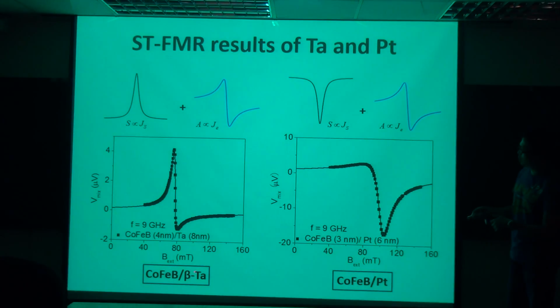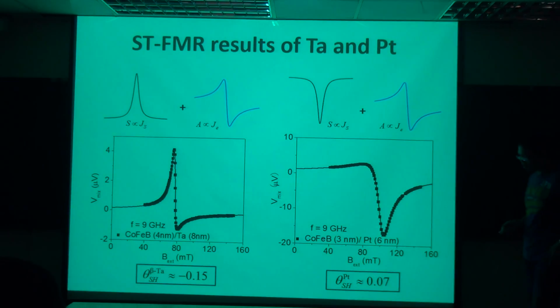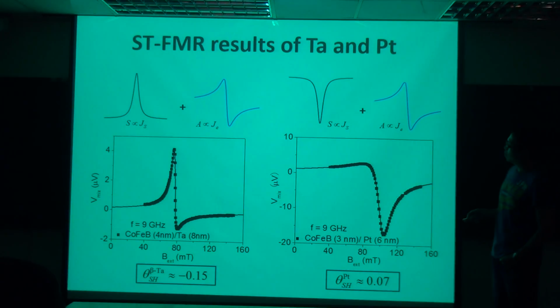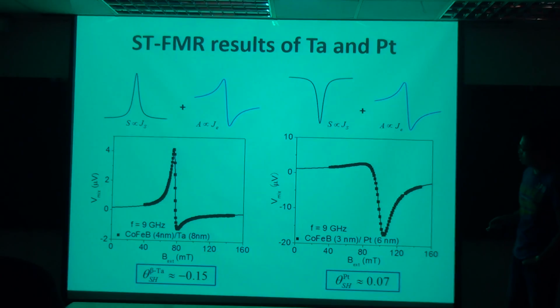And so for tantalum, it has this symmetric part pointing upward, and for platinum, it's pointing downward. So tantalum and platinum should have opposite signs of spin Hall angle. And if you believe that, and you analyze the ratio of these two, you'll get a spin Hall angle of tantalum about minus 15%, and for platinum it's about 7%.